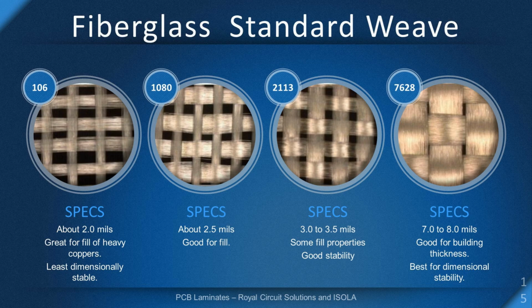So your 1080 is another good weave for filling. And then you get to your 2113s and even your 7628s, which will not be beneficial to try to fill the heavy copper, but they're very good for maintaining thickness and building a big, thick dielectric between your layers. And they're also very good to maintain that dimensional stability. So this is where you're going to try and work with Royal and other fabricators to determine what the best stack up to use for your particular design is.